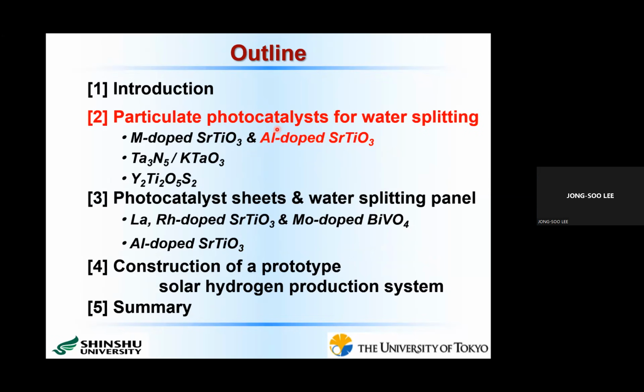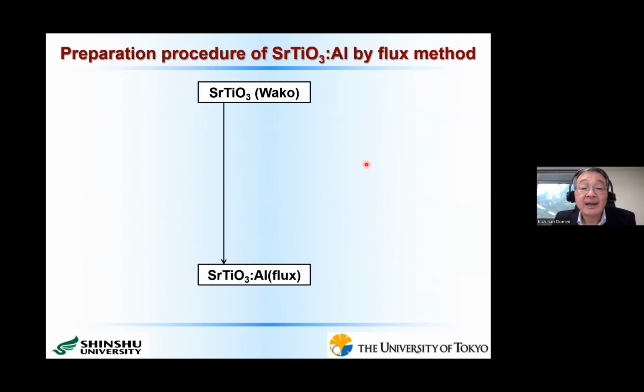This aluminum 3+ cation replaces this titanium 4+ cation. So this is the lower valent cation doping, and we can expect that the activity will be enhanced. In addition to that, here I would like to show the so-called flux method preparation procedure.